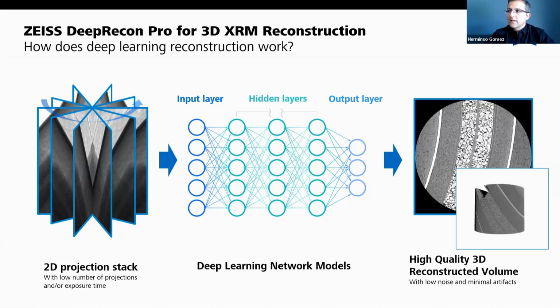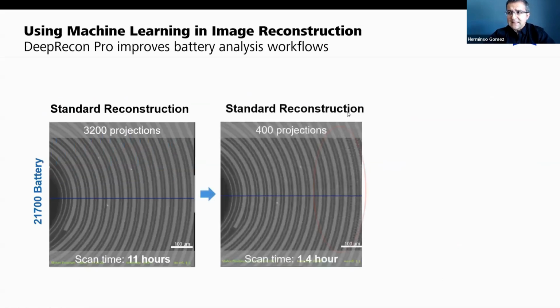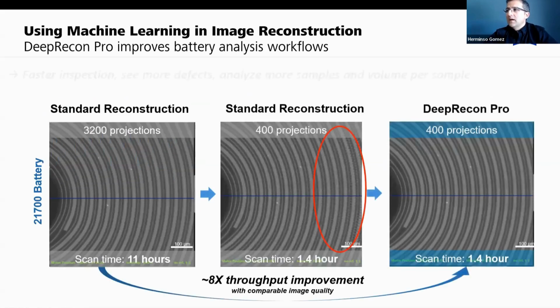A way around that is to train a network to identify what is noise when you start decreasing the projections from actual data, and get rid of the noise. So you enhance the data, and then you can go backwards and start cutting the projections to below 2,000, to the hundreds, maybe 500 or 300 projections, and see if the data is really good quality. And we've done comparisons, and this is the way to speed up the scan.